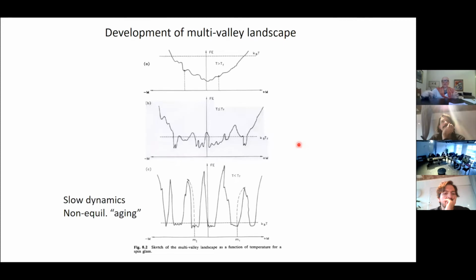Now, here we go over to what Parisi is saying. What is coming out of Parisi's theory of an infinite number of order parameters is this type of formation of a multi-valley landscape. This is the key interpretation. This is a coarse-grained schematic here. But even in these valleys, which represent frozen-in states, there are mini valleys. And the system can still fluctuate around these mini valleys. And finally, if I go to very, very low temperatures, I get a bunch of these valleys which lock the spin glass in. So in order to get a physical interpretation of this multi-valley landscape, this immediately generates from the infinite number of order parameters. This immediately comes out of Parisi theory.